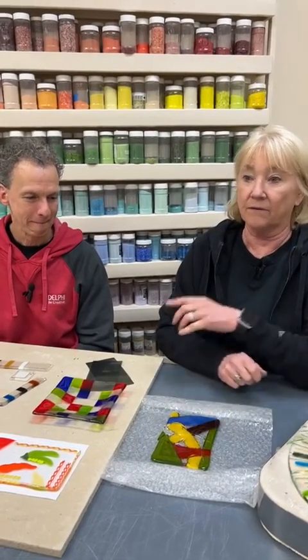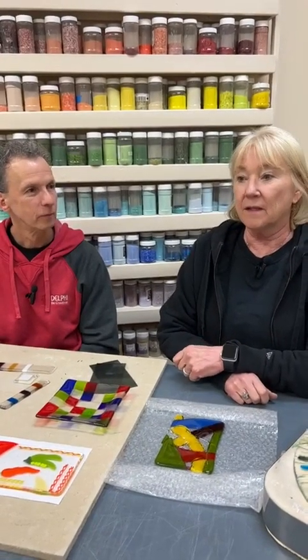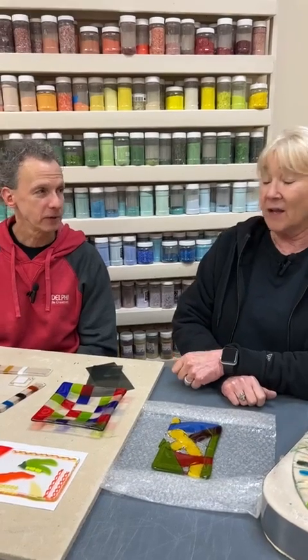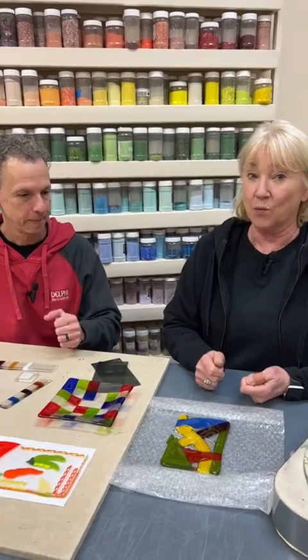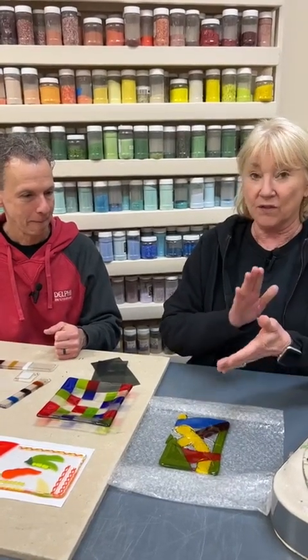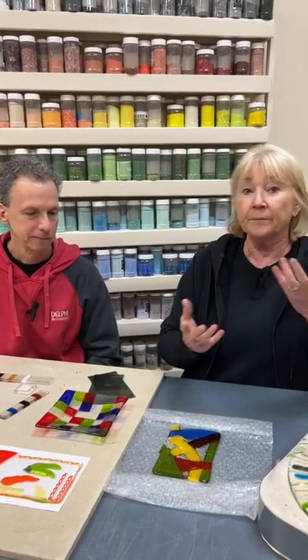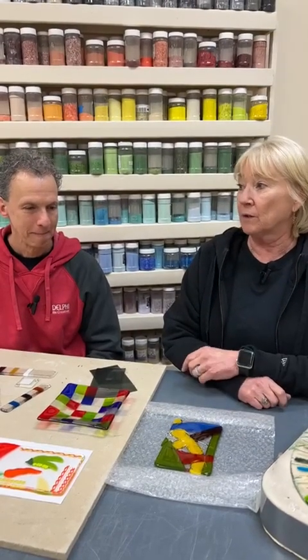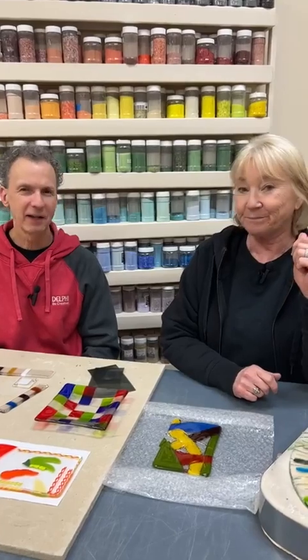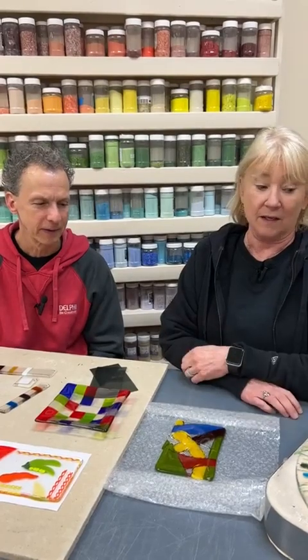I know this is kind of not fun if this kind of thing happens, but it's also a little different than a thermal shock crack too, right? Yeah. Much cheaper. So it's interesting to learn these things because then you can start to assess what went wrong. If it was more just a clean break, it's probably something caused by a temperature issue, too hot too fast, too cool too fast. But if it becomes more spider web or has some real direction changes, I say that if it has a path to it, then more than likely it's incompatible, and I would look for that.